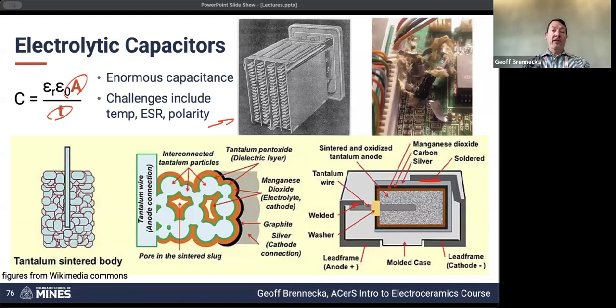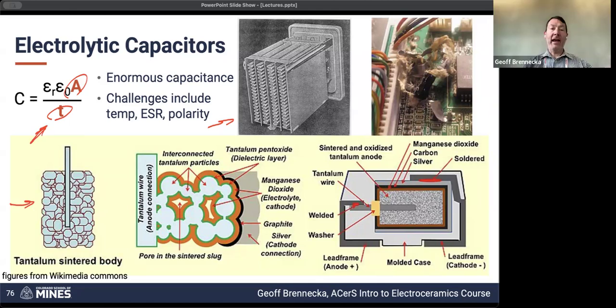So you can start with even packed powders, as shown down here, of either aluminum or tantalum. Those are the most common. There are several other varieties as well. So you can end up with a massive surface area that can give you a very large area, and you can adjust the thickness of the oxide layer that you grow on top of this by how you do the oxidation. So one example is you just put it in air and heat it up. That's an extremely crude approach, but it does work. The more sophisticated versions are to actively chemically anodize. So you could put it in an electrolyte that you use to drive the oxidation.